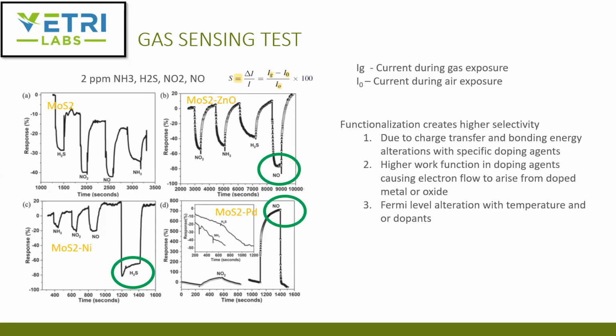And the same can be said about nickel, there is a clear separation with hydrogen sulfide. So moly sulfide doped with nickel has a clear signature with hydrogen sulfide, so it's more selective to hydrogen sulfide. Moly sulfide with palladium is the one material they show where the response actually goes the opposite way.